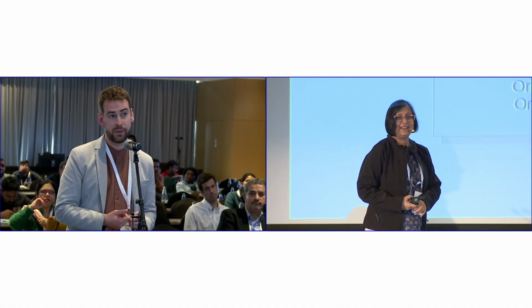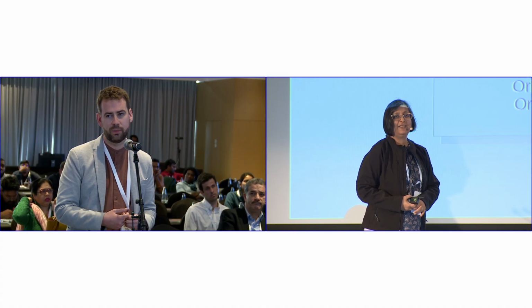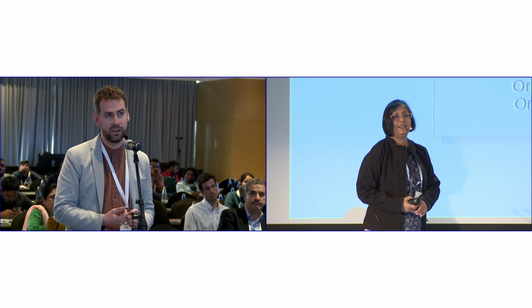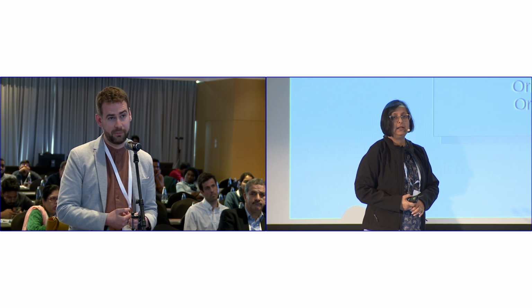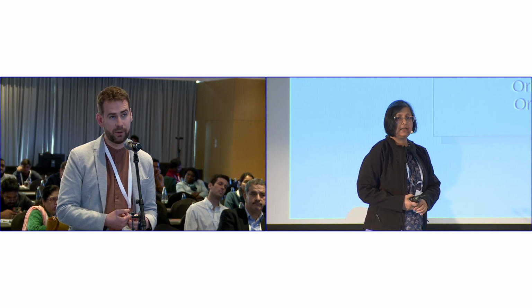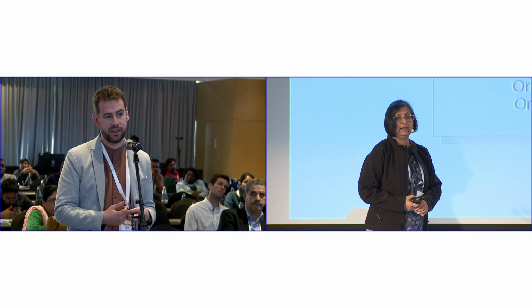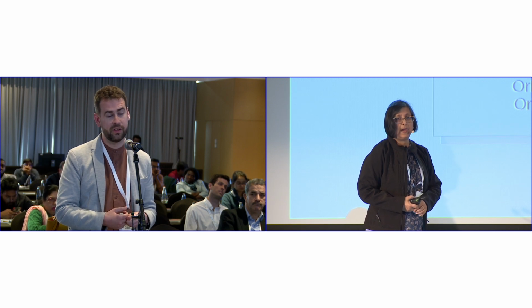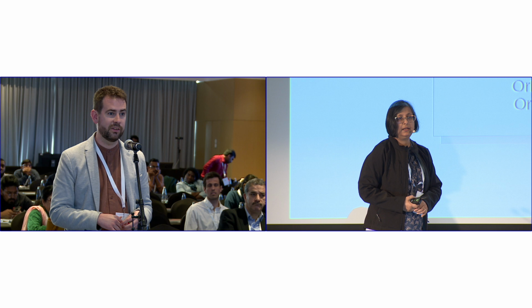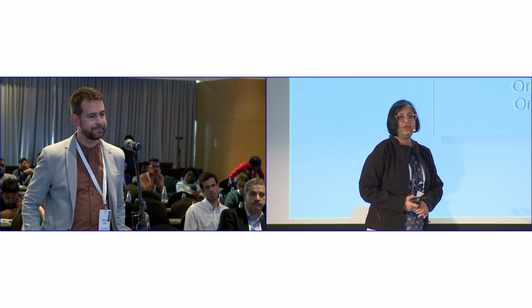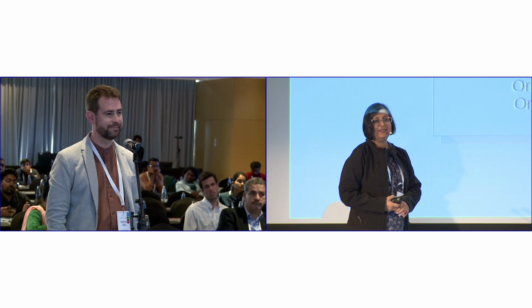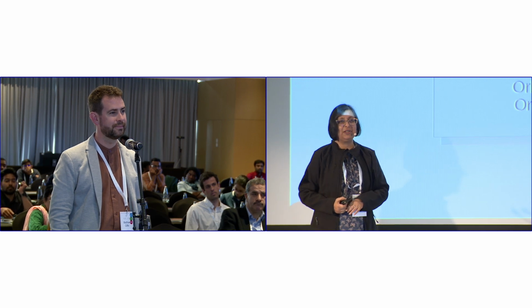The other complicating factor, which is also probably pretty interesting, is the tendency for defects, particularly metal site vacancies, which are pretty ubiquitous. Obviously, depending on the A-site cation you use, you can suppress them to some extent, but that's been a big challenge. So the most important defect will be the anti-site defect, and that can be calculated, but we need the impetus from the experimentalists. Otherwise, it feels like we are just going ahead. Thank you.